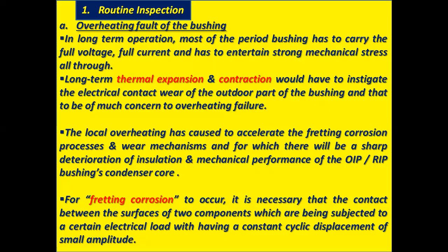The local overheating causes acceleration of the fretting corrosion process and wear mechanisms, and for which there will be a sharp deterioration of insulation and mechanical performance of the oil impregnated paper or resin impregnated paper bushings condenser core. For fretting corrosion to occur, it is necessary that the contact between the surfaces of two components is subjected to a certain electrical load with a constant cyclic displacement of small amplitude.